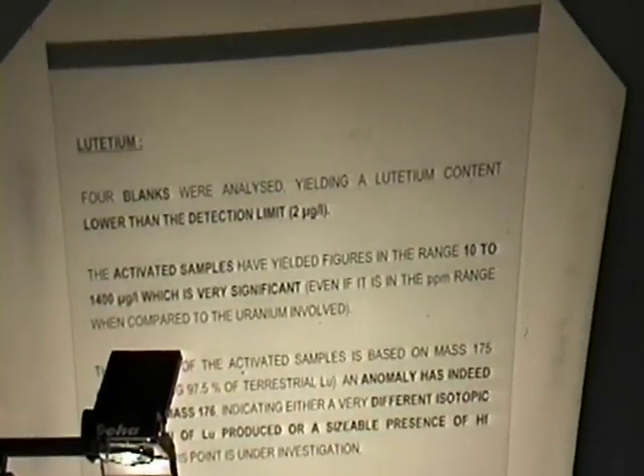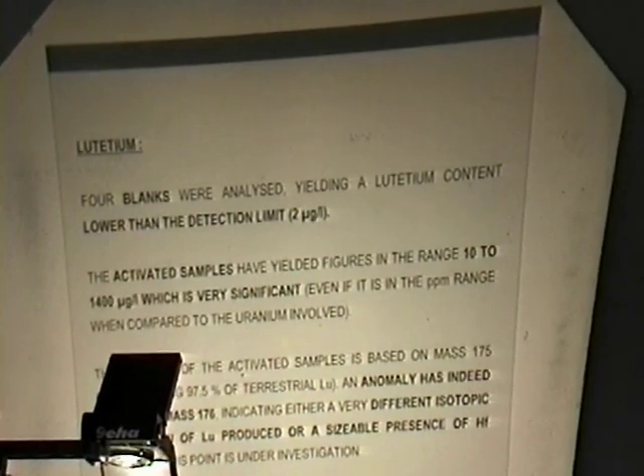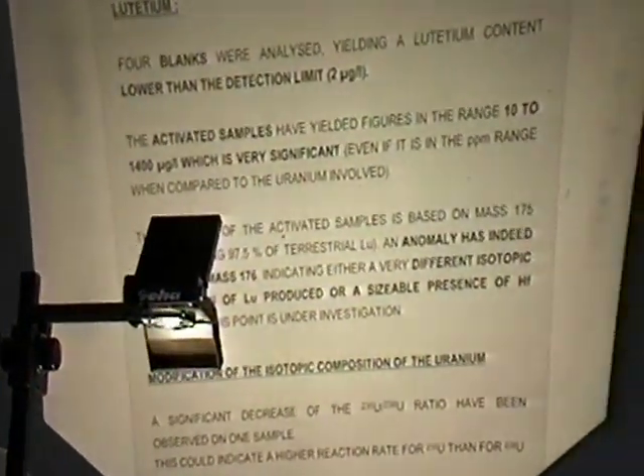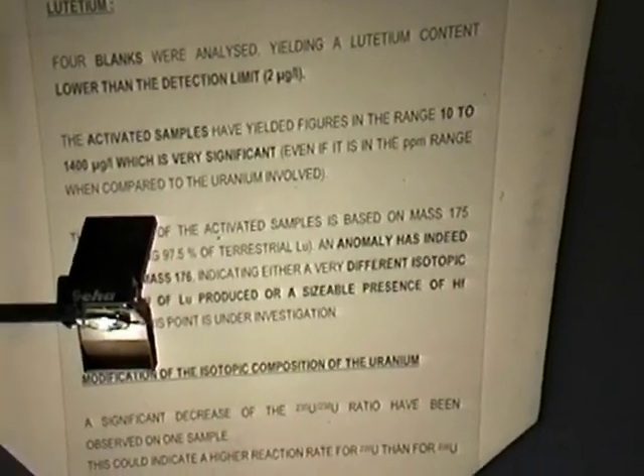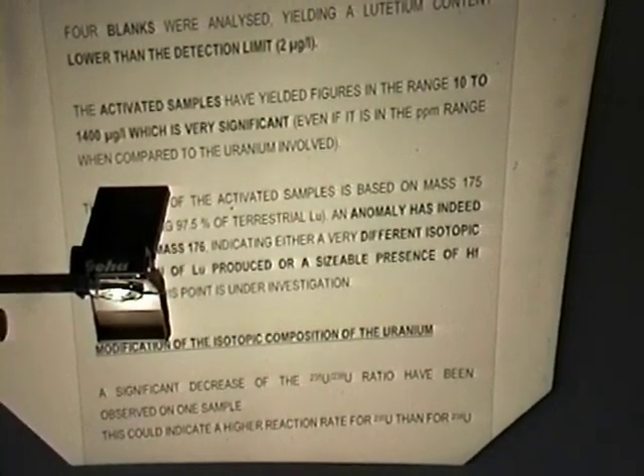Then if we turn to the lutetium, it is, as I told you, in the ppm range, but it's extremely significant because the detection limit is 2 micrograms, and we have observed up to 1,400 micrograms of lutetium in the solution. And moreover, there is a second thing which is extremely interesting. This lutetium has a very different isotopic composition, because we have a huge quantity at mass 176, which usually is only 2.5%. So this excess is either the signature of a modification of the isotopic composition of the lutetium, or a signature of the production of ytterbium and hafnium, which are the two elements around lutetium. So we can say that unexplained lutetium has appeared in our samples.